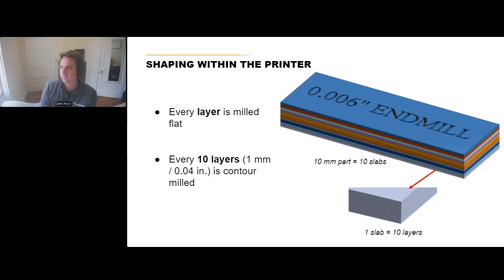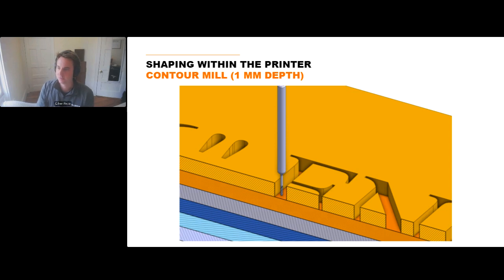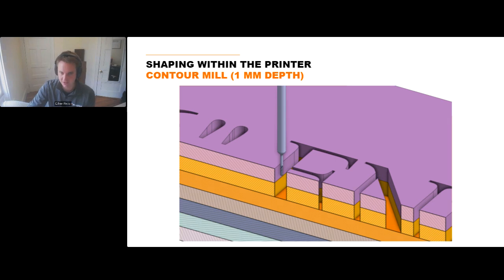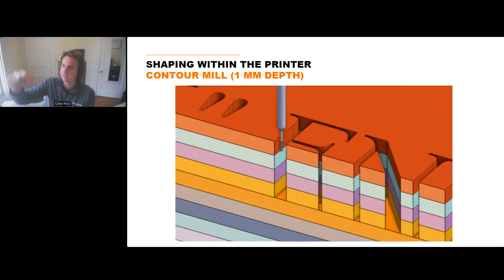So every single layer is being milled here, and I oversimplified it a little bit in my demonstration here, but actually every 10 layers we're going through and doing the contour milling. So you can see after 10 layers have been printed, we go through and do that contour milling, and this really enables us to do these really deep ribs, because we're printing and machining, printing and machining to get these really deep ribs printed that you would never be able to machine on a wrought piece of tool steel, just because the aspect ratios are too extreme, which is very common in injection mold tools, and that's why they use so much sinker EDM.